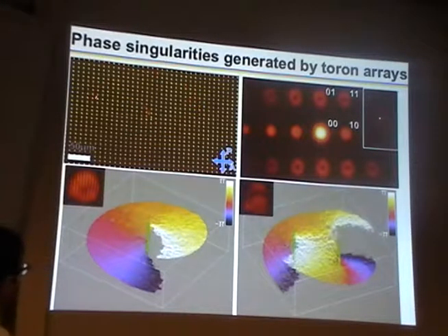You would then be able to use it as a diffraction grating again, but after looking carefully at what you get in the diffraction pattern, you would notice that all the laser beams in the first diffraction order would have dark spots in the center. This is already indicative that what we got are optical vortices, right?